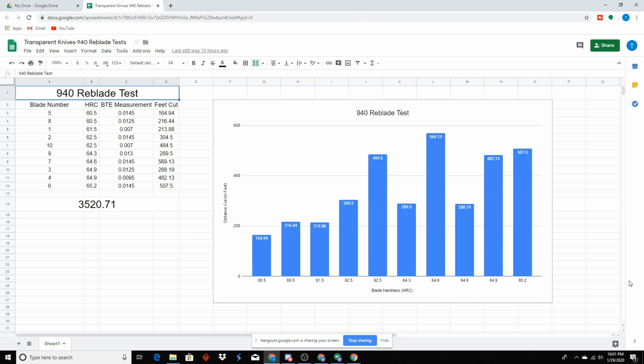In addition, from 50 HRC all the way up to about 62 HRC, I would say it's pretty much linear, probably. As far as HRC goes, as long as you're doing the same conceptual heat treat, you're not doing wildly different tempering temperatures or wildly different soak times, as long as you're trying to do the same thing, HRC is pretty much going to predict performance. So that would be my takeaway. I think some people are going to look at this and be like, see, HRC doesn't matter at all, and that's really not what I want to get across.